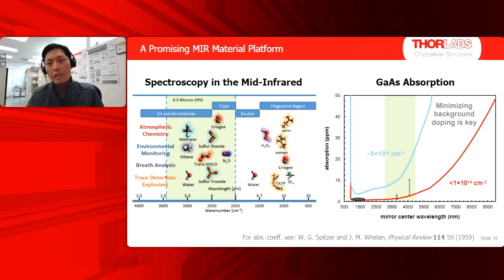So our gallium arsenide platform is well suited to moving to the infrared. What I plotted here is the absorption as a function of wavelength. You'll see that it's very difficult for us to go to the visible, but we can maintain low levels of absorption, well below tens of ppm, out to nearly 10 micron center wavelength. And the key here is just in the material growth, to keep the background doping levels during the MBE growth very low, and that's how we maintain these low absorption values.